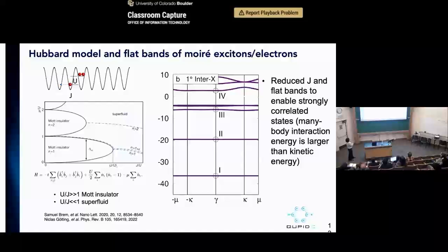The J is defined by the tunneling between sites, between Moiré sites. This is a calculation done on these Moiré superlattices, and if you look at the exciton bands, they become very flat. In condensed matter, this is known as flat band physics or strongly correlated physics. Instead of a parabolic band where the excitons move very fast, they have much slower motion. Now you start to get into the strongly correlated regime, where you can think about realizing a simple model like the Bose-Hubbard model using this exciton.